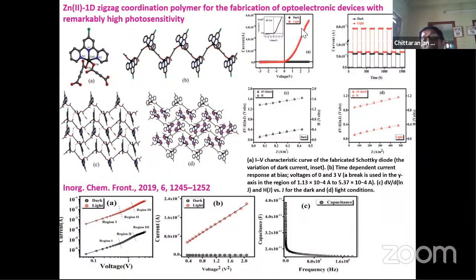This is in the presence of light. You see that the dark phase is almost non-conducting, while in the light phase its conductivity is enormously increased. And this conductivity change is also recorded by the current-voltage relationship, where you see there are three regions. Region 1 is the common ohmic, while regions 2 and 3 show Schottky diode behavior.